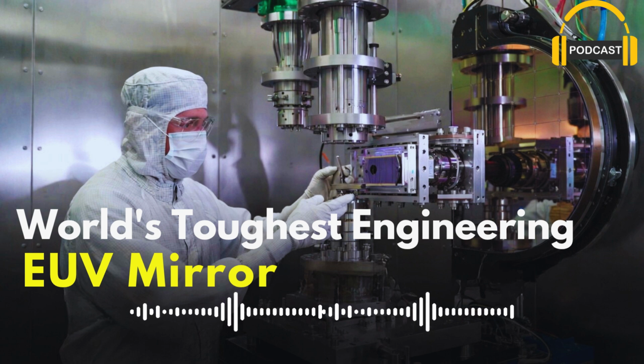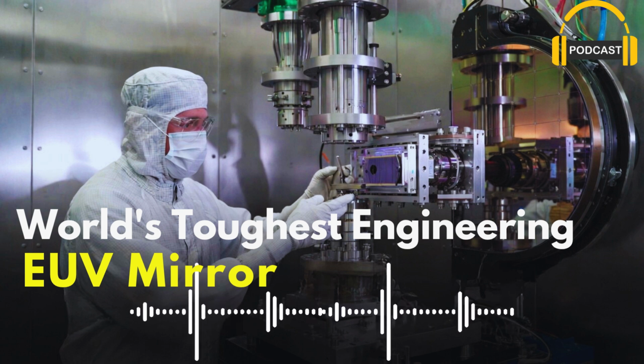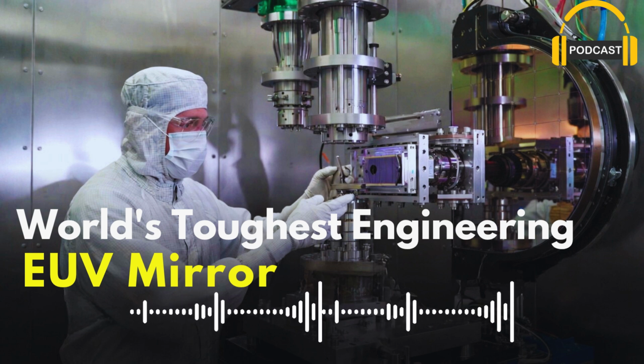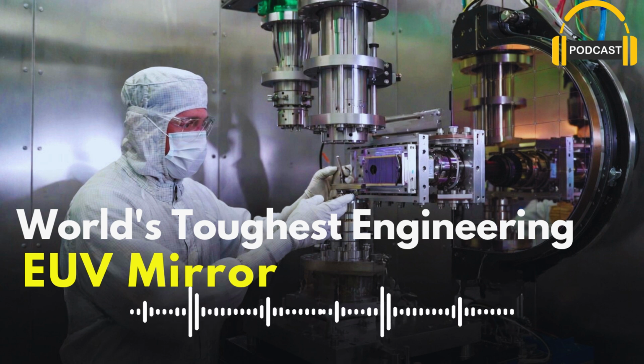In 1971, Spiller used a computer to simulate what would happen if you stacked just a few layers of different materials. The math looked promising. So he actually built a small mirror with only 6 layers using magnesium fluoride and gold. It wasn't great, but it reflected a tiny bit more than a single layer would. That was the first proof multi-layer mirrors for extreme short wavelengths could actually work.